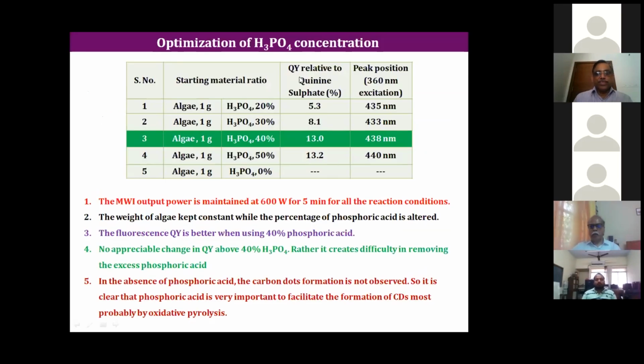Now, when you synthesize all this material, optimization of parameters like the input material is needed. So if we have taken phosphoric acid as material, we have optimized the concentration of the phosphoric acid, varying the percentages. Now, our reference is the quantum efficiency. When do we get the highest quantum efficiency? That is the condition we call the optimum condition for the synthesis of the carbon quantum dots.